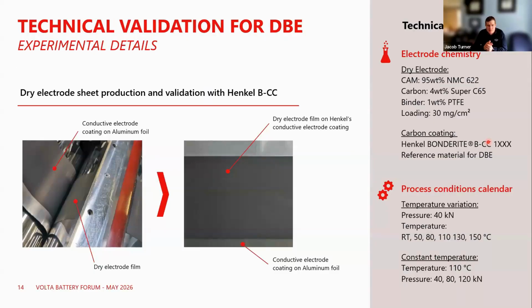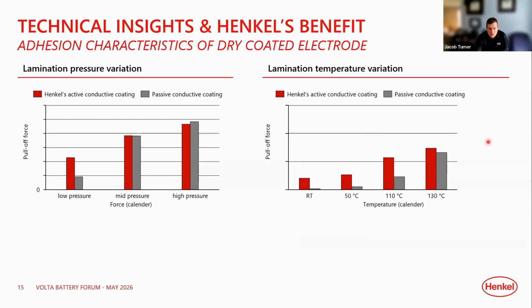So when we take the next step for the technical validation, Henkel, we don't do dry electrode type processing, so we worked with a research institute to do some of these studies here. You can see the dry electrode formulation up there in the upper right. And we're going to be comparing our 1000 series, this active primer concept, to that of a passive primer concept reference material under different temperatures and pressures and looking at adhesive strength and how conductivity is impacted. So when we do this, you'll notice that if you push really high temperatures and high pressures, you can get them to adhere similarly.